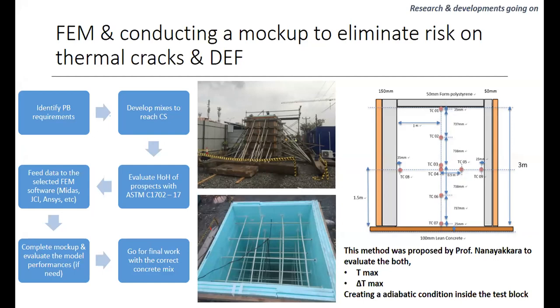Then we can develop concrete mixtures to get the required compressive strength. And then we can evaluate the heat of hydration with the new ASTM codes that have been generated. Utilizing this, we can identify the generation of heat of hydration. And there are a lot of finite element modeling tools, like MIDAS, JCI, Japanese guidelines, ANSYS, etc., to model the concrete element with the support of heat of hydration data. Then we can identify, if a mock-up is required, the suitable mix design. Otherwise, we have to do a lot of mix designs to identify the suitable concrete mix design which can develop the required compressive strength as well as the other temperature parameters.